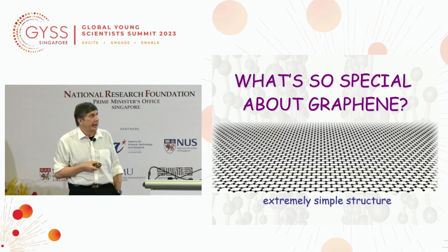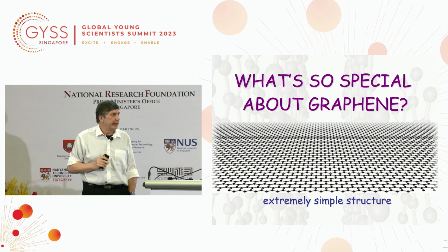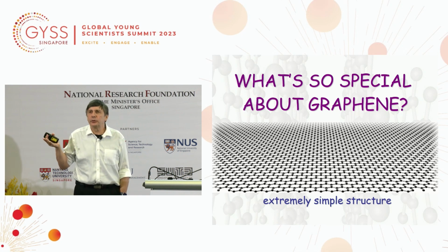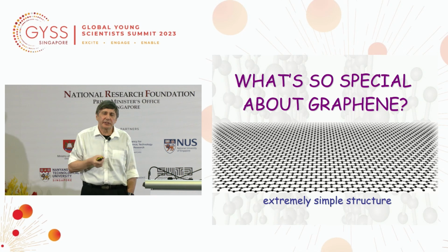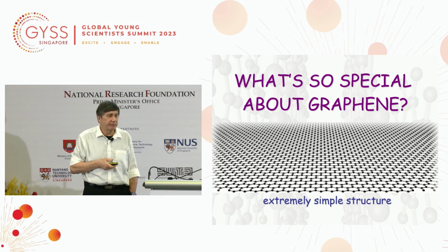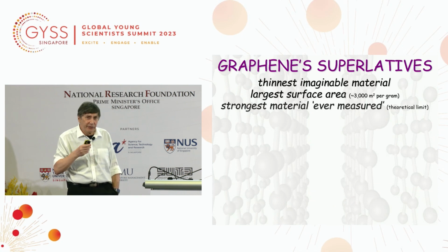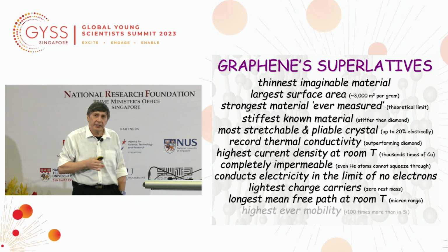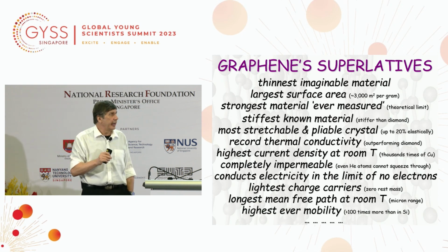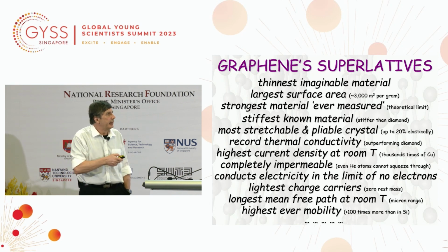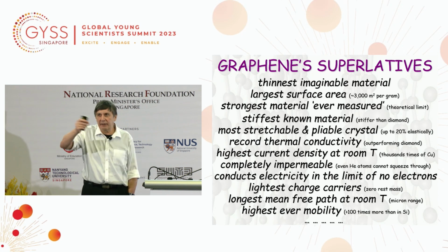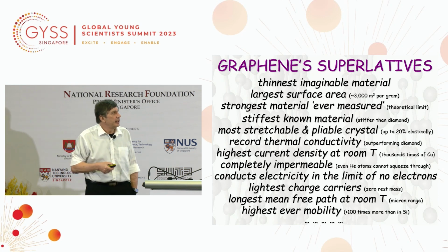Okay, so what? We make those monolayer carbon sheets, extremely thin structures, and one says, so what's so special? It's nice that we can extract atomic planes, but so what? If it were just this trick of extracting atomic planes, I probably wouldn't be here. It would be just a scientific curiosity. But then over, say, 3-5 years, we started looking at the properties of this material more carefully and found out that it's extremely unusual. It turned out to be not only the material with the largest surface area, 1 gram covers a few football pitches as we measure surface in Manchester,